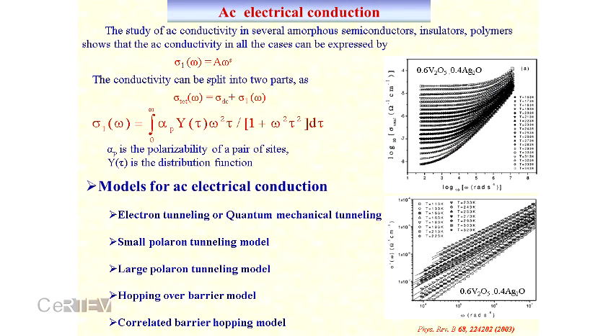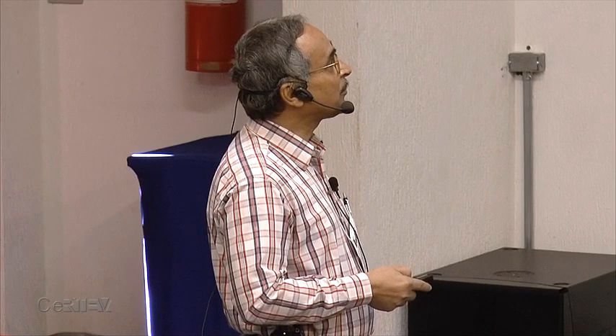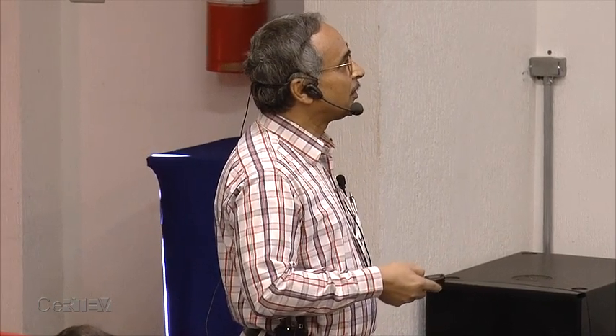And then what about the AC conductivity? For the AC conductivity, you can see here the measured AC conductivity as a function of frequency. At low frequency, it is almost independent of frequency. But as the frequency goes up, it shows a dispersion. If you subtract the DC conductivity from the measured total conductivity and plot it again, then you can get straight lines. What does it mean? The pure AC conductivity is showing a power law. We can describe the data as A times omega to the power s.